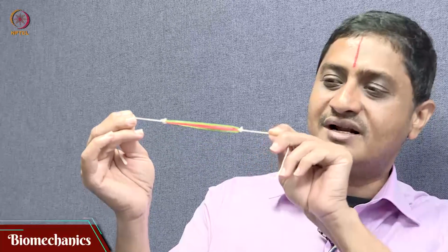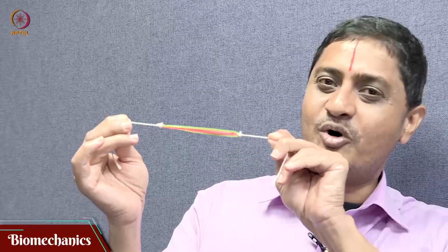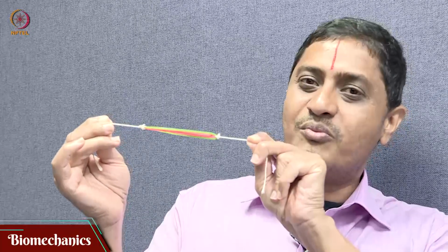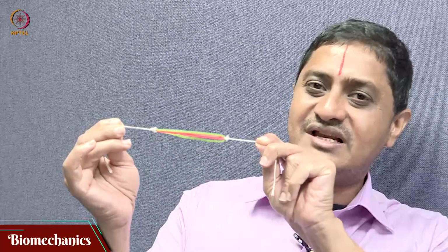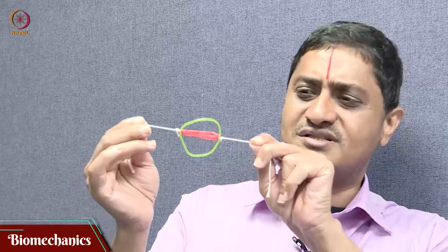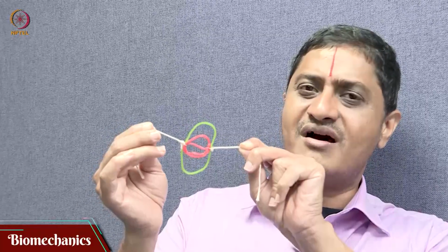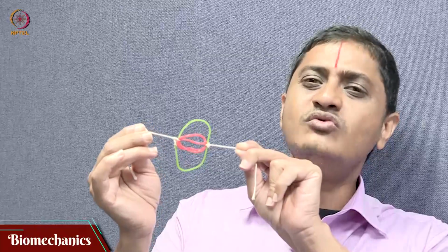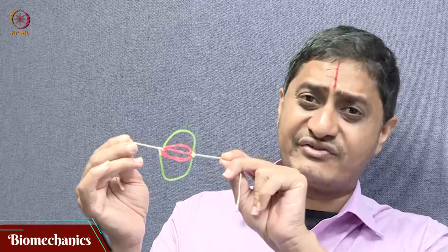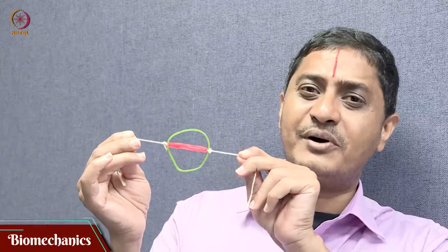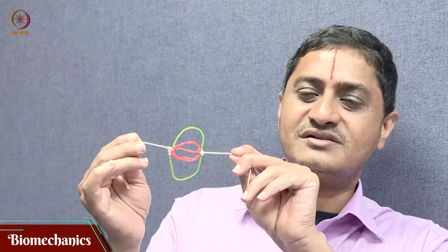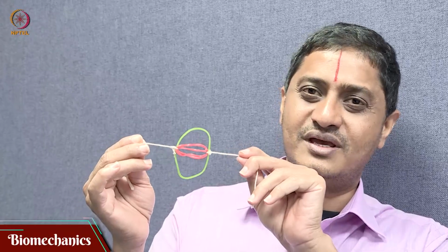What you are seeing is that at approximately this point, both the red and the green band are recruited. Now, both these bands, although they are having linear elasticity, are getting recruited at two different resting lengths. Of course, this is just two. In the case of the tendon, you are going to have thousands of these fibrils or millions of collagen fibers that uncrimp at different lengths, giving rise to a form of non-linearity that arises due to linear properties. Okay.